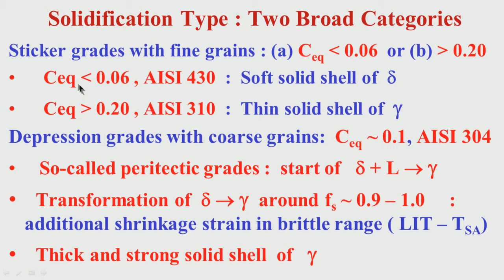And for low carbon equivalent and low nickel equivalent by chromium equivalent, that means 430, you have a soft solid shell because it is delta. So that also cannot resist ferrostatic pressure strain, so it is a sticking tendency. But when the carbon equivalent is around 0.1, or AISI 304 having nickel equivalent by chromium equivalent around 0.55, slightly more than 0.55, you have depression, so you have relatively coarse grains.